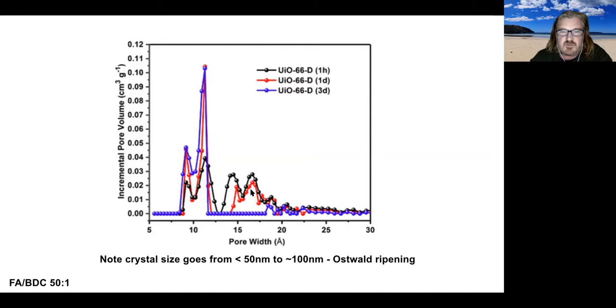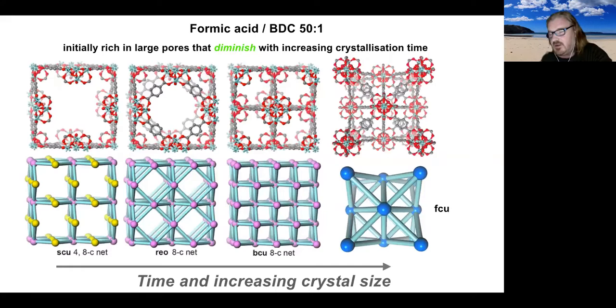But in particular, we now have a distinction between crystals which we can extract earlier on in the synthesis, which have missing clusters, and those taken from later on in blue, where we have no missing clusters. So we can make a distinction between the catalytic behavior of the missing cluster type defect and the missing linker type defect. The defect formation energies can be used to rationalize what we've just seen. These scu and reo type nanophases have the largest formation energy. bcu has the smallest formation energy. So we think over time, what's happening is that we're seeing an infilling of the defective material, which tends towards this perfect material.